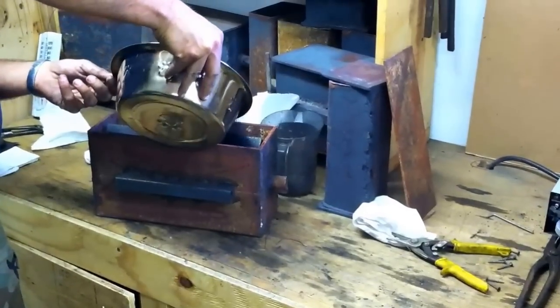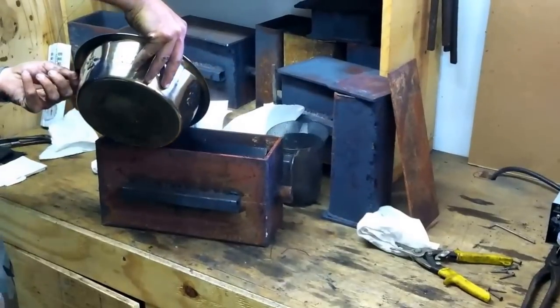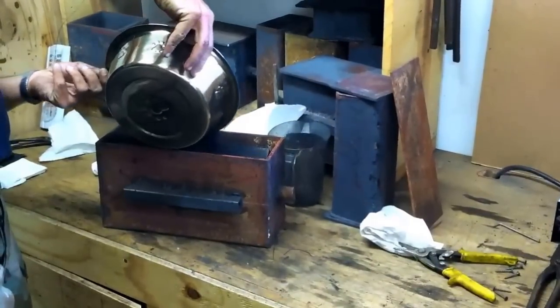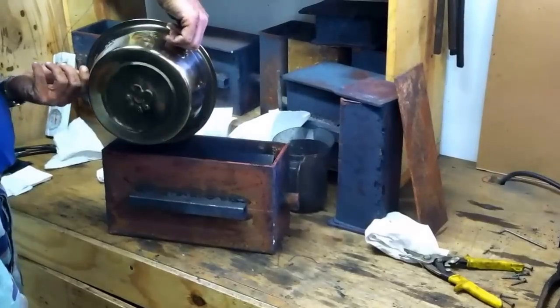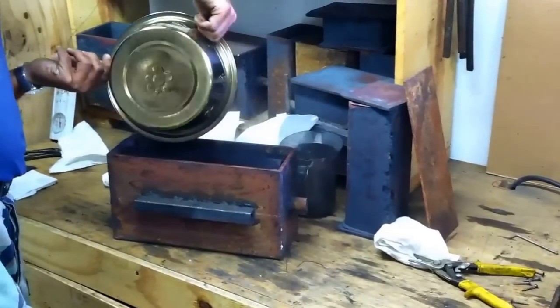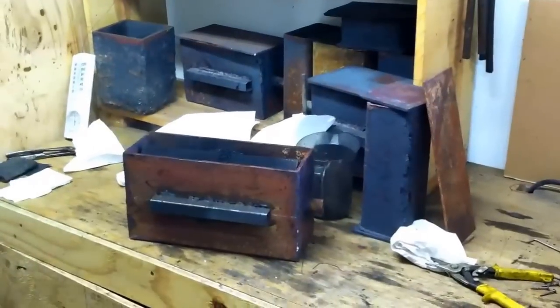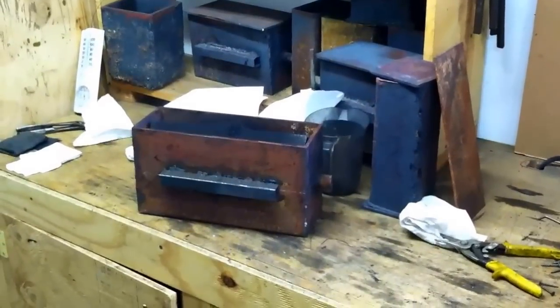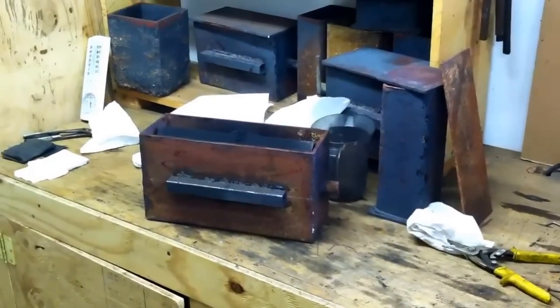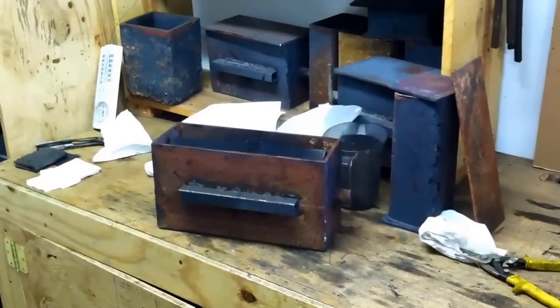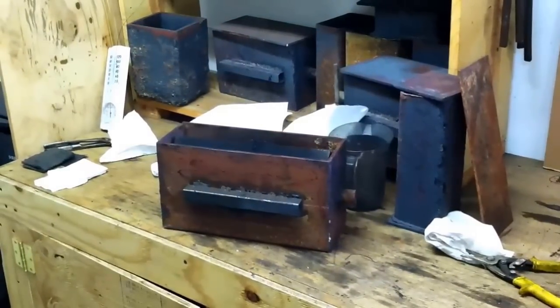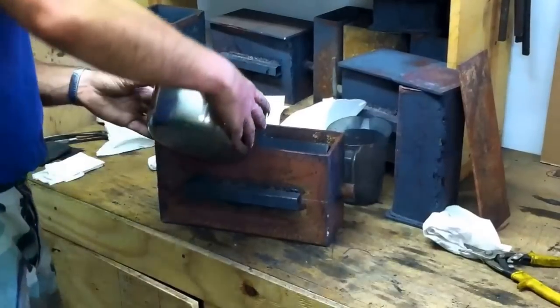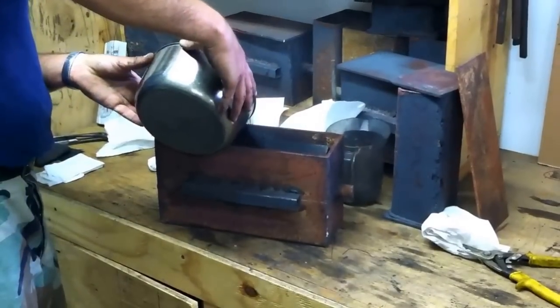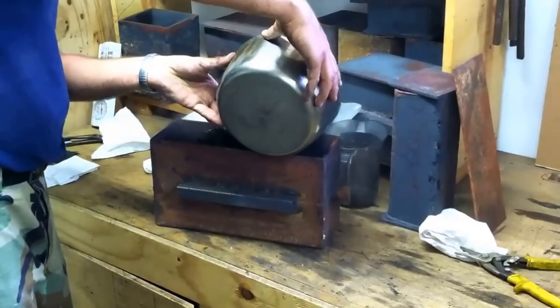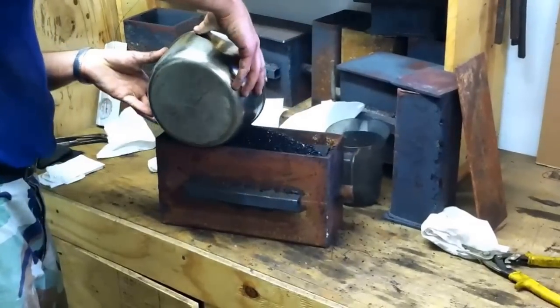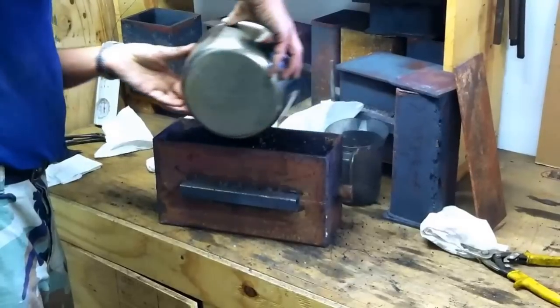Our charcoal mix here is 1 part wood charcoal and a 1/2 part bone charcoal, I think, is our mix. 1.5 wood to 1 part bone charcoal. And we've dehydrated this charcoal in a kitchen oven for a good period of time to get all the moisture out of it before we start the process.